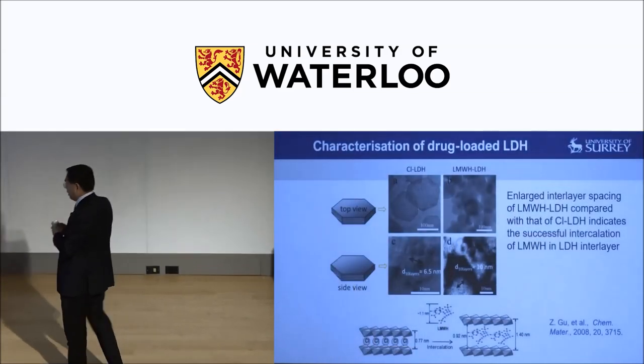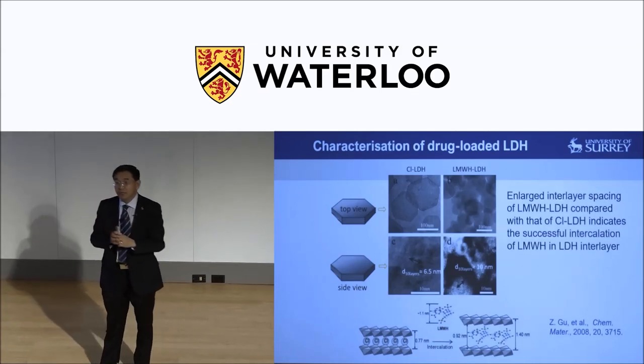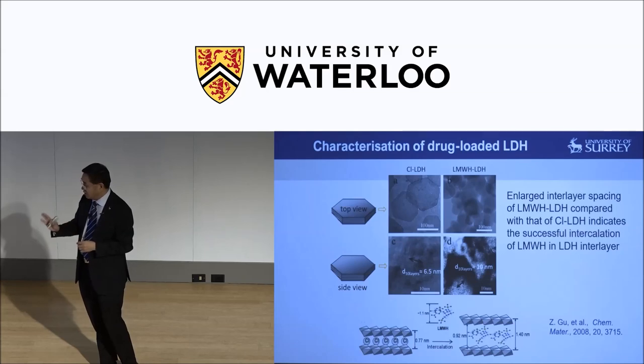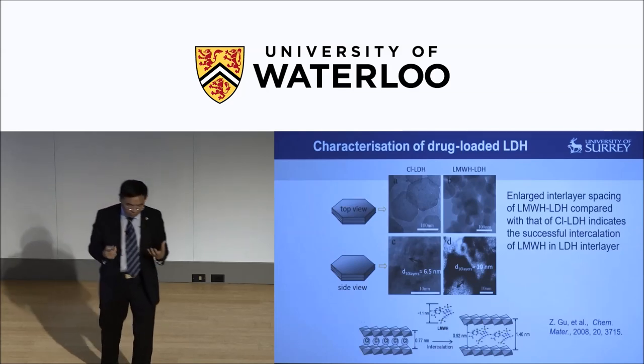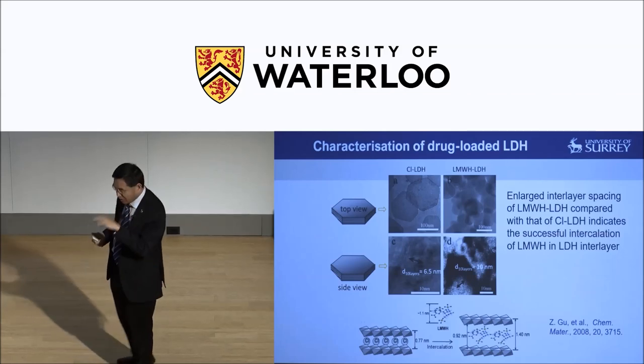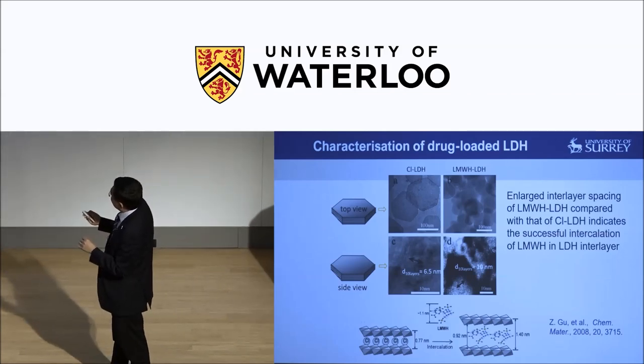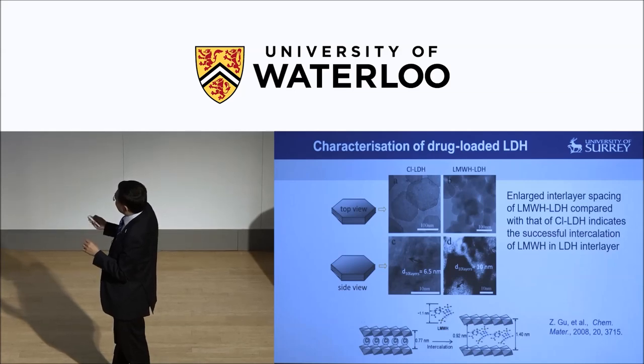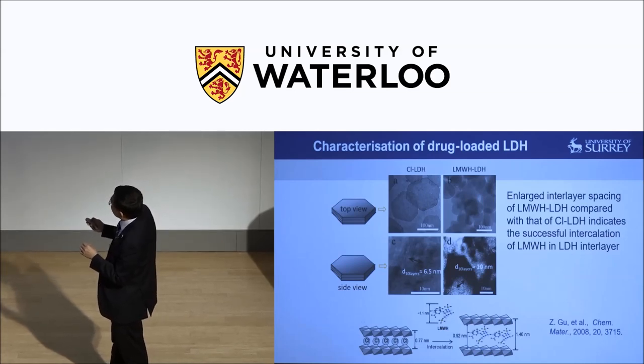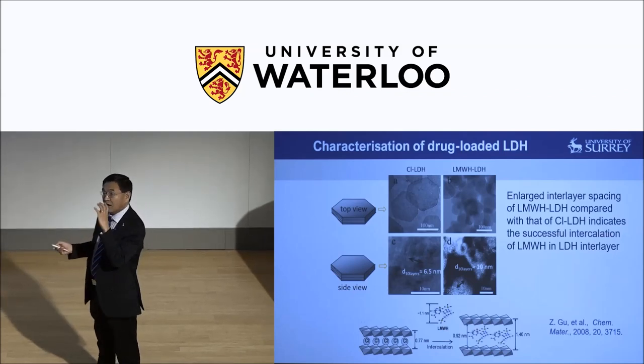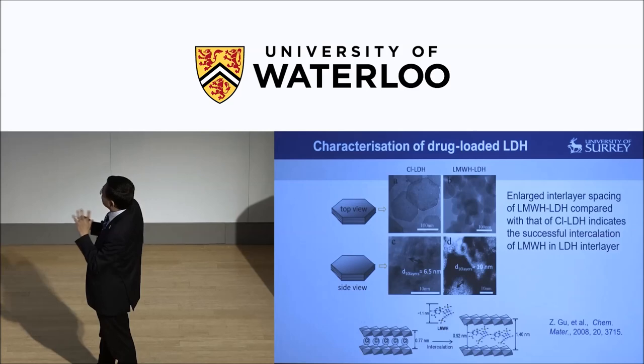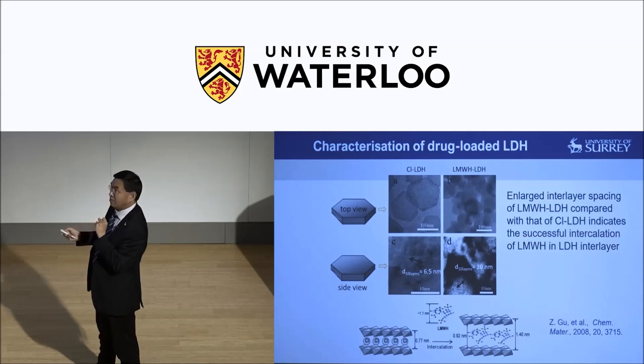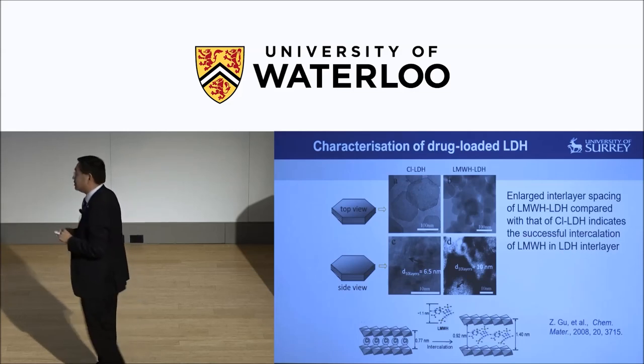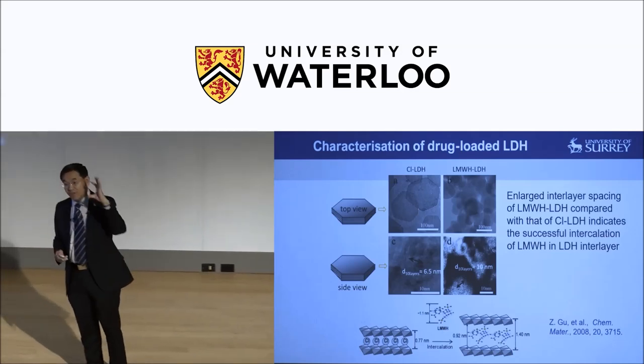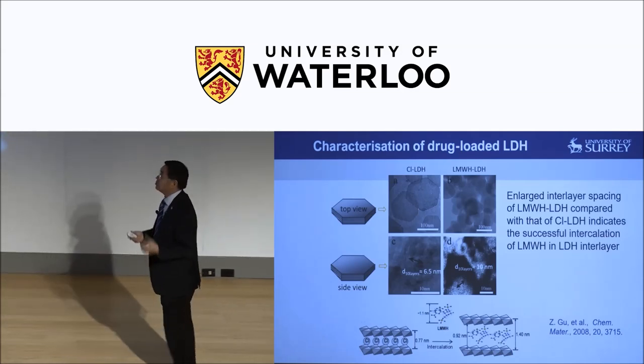We use this as a drug carrier. You can see that when you load drug, this is a low molecular weight heparin, which is a cardiovascular drug, you load it into the interlayer because this is an anion exchange, so you can see the expansion of the interlayer spacing. The XRD can give you the quantification, but you can also quantify by high resolution TEM and get quite good correlation in terms of the loading amount and the d-spacing enhancement or enlargement.